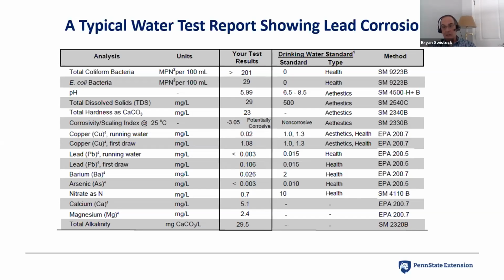Similarly with the lead, the running water lead was below detection, but yet it had over 100 parts per billion of lead in the first draw sample, 0.106 milligrams per liter, or 106 parts per billion. So this is a very classic case, and we see samples like this all the time. Very, very clear indication that the corrosion of the plumbing is what's causing the problem here, because we have no lead in the running water sample, but we have lots of lead in the first draw, and we've got a very corrosive water supply.